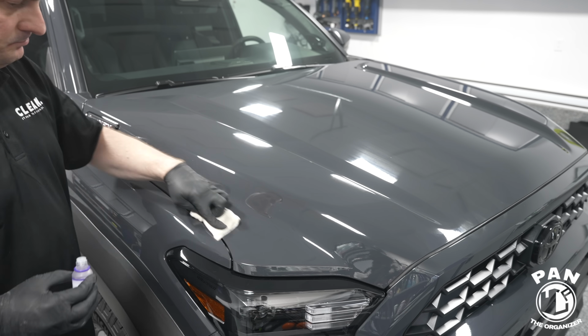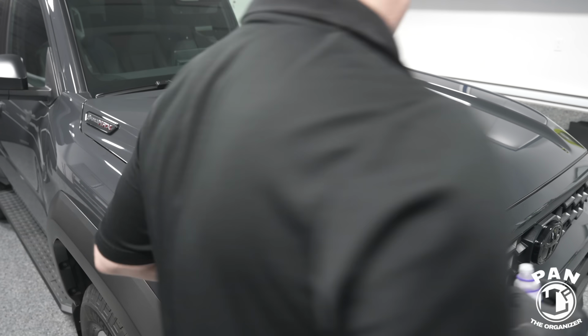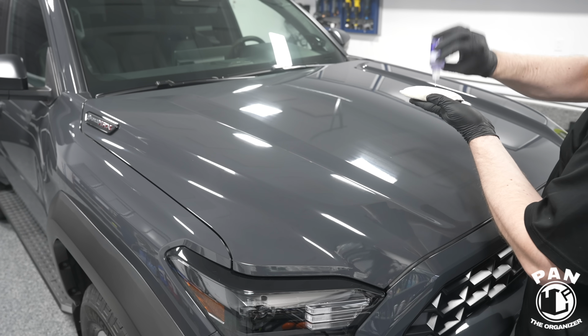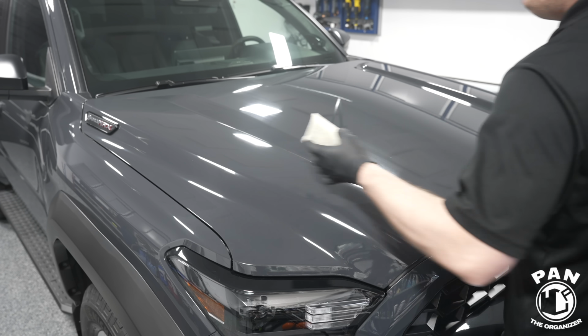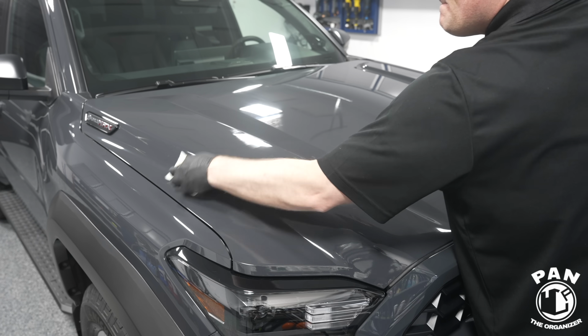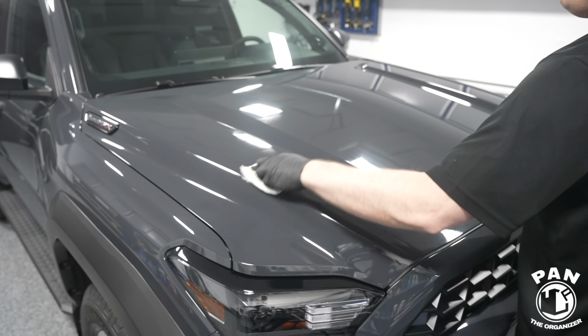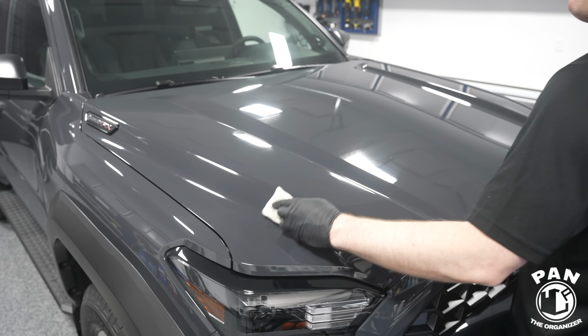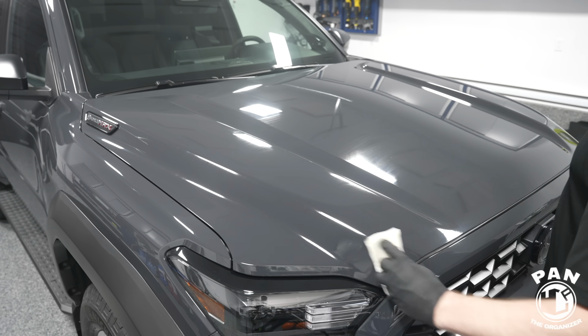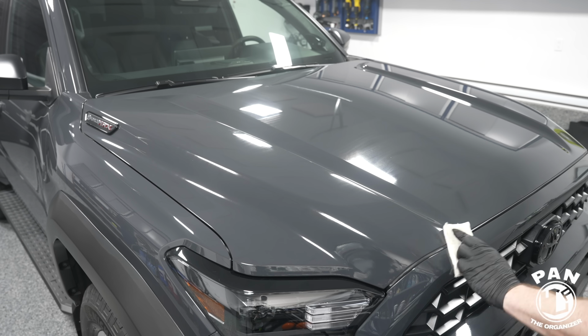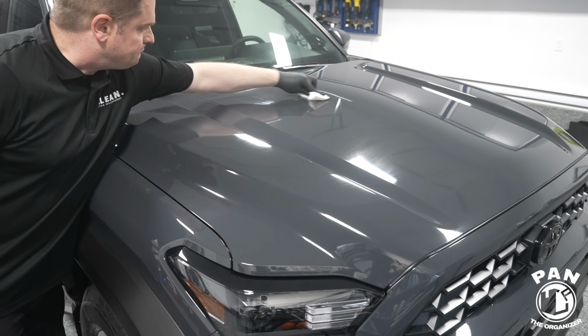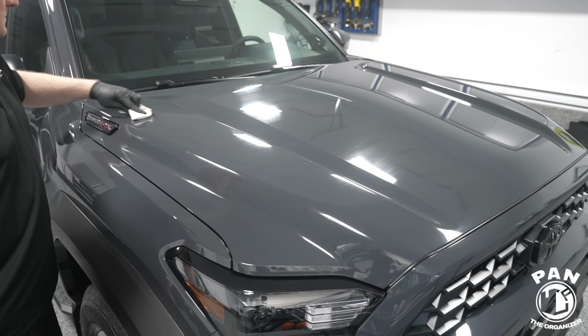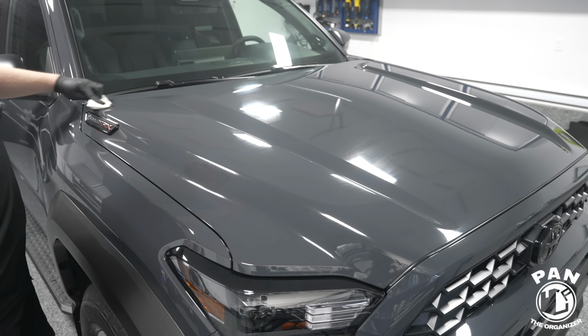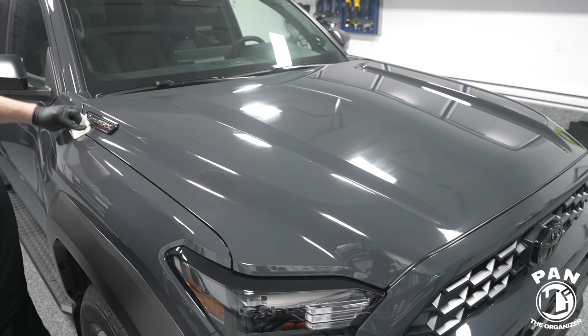So in a motion of a cross hatch pattern or basket weave, so up and down and left to right, you're applying the coating on the surface. Now with this specific coating, make sure to leave it for at least 1 to 2 minutes on the surface before starting to level and do the final buff because you want it to bond correctly. So even though it's going to flash quickly, you're going to see the rainbowing sometimes in under 30 seconds. Make sure you leave it for at least 1 to 2 minutes on the surface before you wipe. I work in 20 degrees Celsius or 68 degrees Fahrenheit conditions and 45% humidity. So you want to be above 50 Fahrenheit or 10 degrees Celsius when you're applying ceramic coatings.